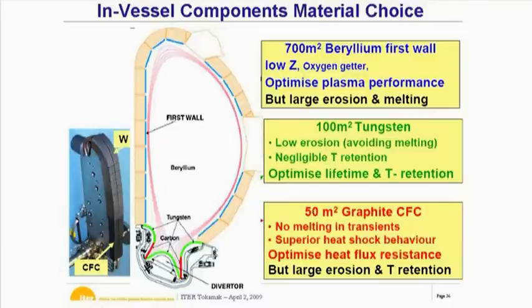Just one thing on materials. The 3 primary plasma-facing materials we have. On all these blanket components here, the blue that you see, this is beryllium. It is our plasma-facing component here. It's kind of the one that over the years has evolved as the best compromise of lots and lots of parameters that you would look at to choose this material. But this first wall is beryllium, so that's our blanket first wall material.